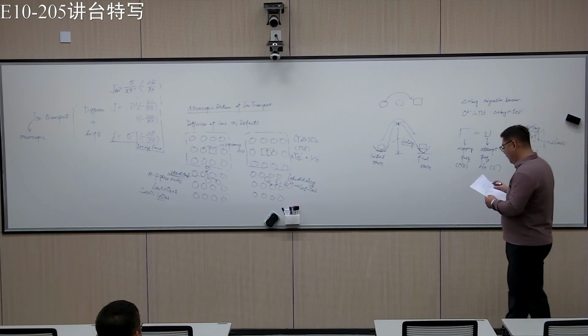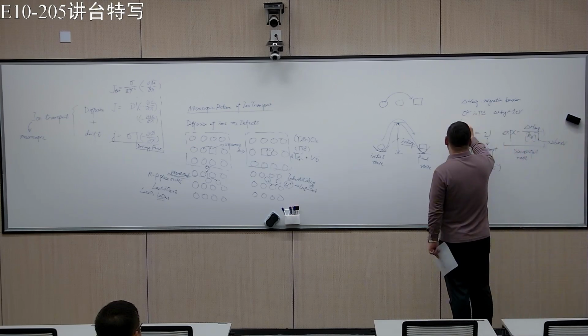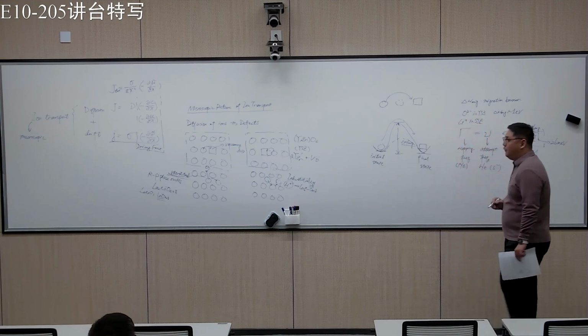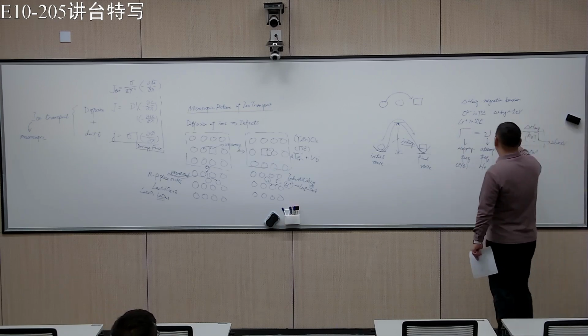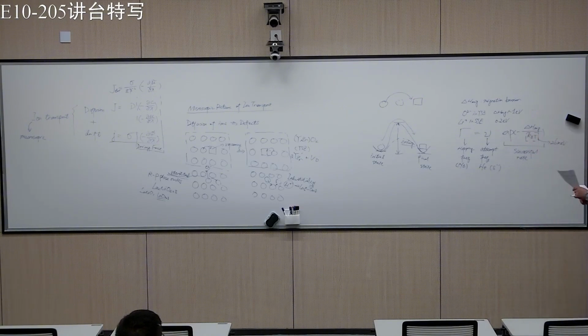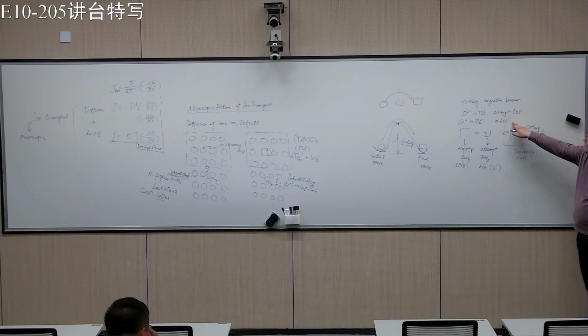Okay, so another example is if you think of lithium ion transport in solid-state electrolytes or solid-state batteries, then the migration barrier is of course much lower. It can be something like 0.2 eV. So now you can see that this is much better, right? If you divide that by the room temperature kBT, the thermal activation, you have a better chance.